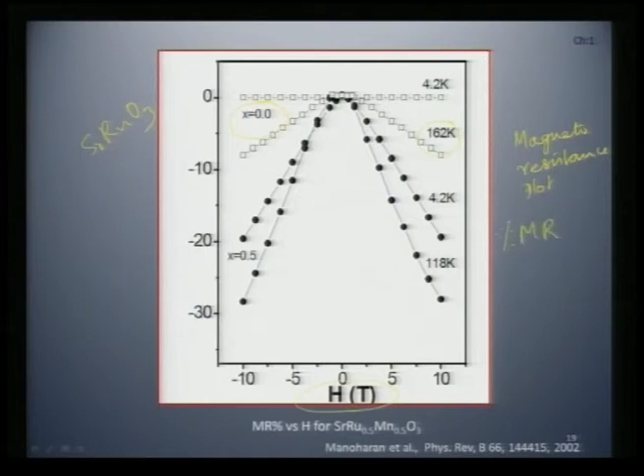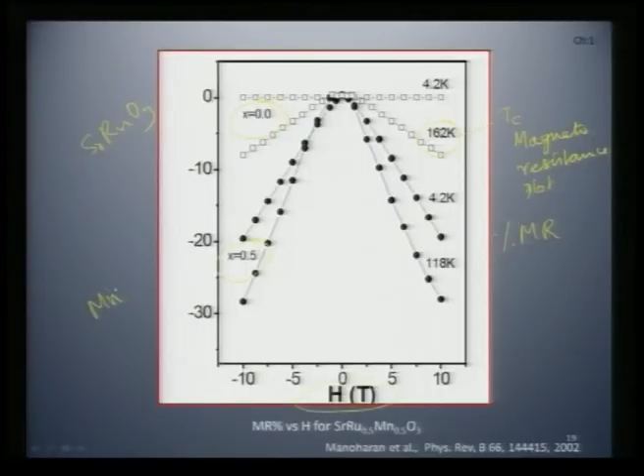percentage MR ratio at the Curie temperature TC is only up to 10% approximately, and at 4.2 K it is still lower. Whereas, in the case of SrRu0.5Mn0.5O3, you see there is almost 3 times the magnetoresistance compared to the parent compound. So, there should be something unusual happening when you substitute manganese in the place of ruthenium compared to the parent oxide strontium ruthenate. We will see what exactly happens.